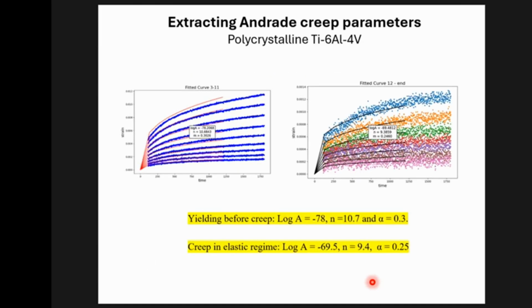And you can extract these creep parameters. This is below the yield. This is above the yield stress, and this is below the yield stress. These results just came in a week or so ago. I've asked the student to see if we can fit them all into one, but you'll find that the stress exponents and the time exponents of the decay are all very similar.